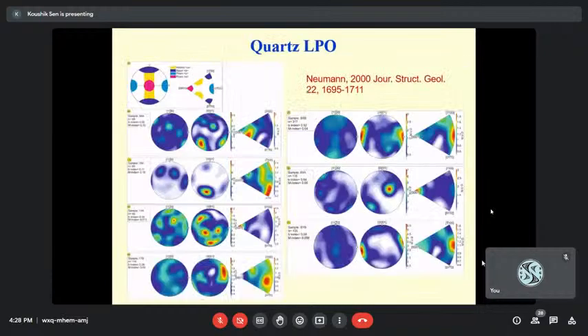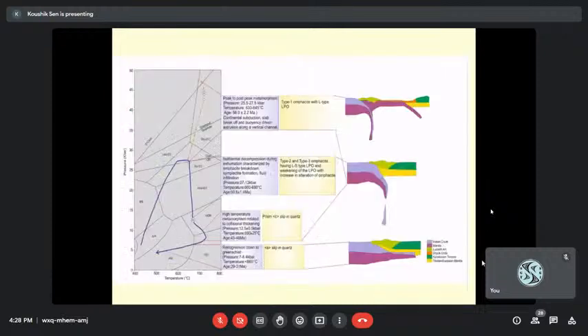Now we want to interpret this LPO in terms of the metamorphic evolution or the PT evolution that we have obtained from previous studies. Now, the type 1 omphacite or type 1 eclogite, that is the freshest of all eclogites, that is the sample 7X, shows an L-type fabric. Now, this can be assigned to the peak metamorphic conditions, say 2.5 to 2.7 gigapascal, when during the peak subduction or peak metamorphism this fabric developed, and this L-type fabric will suggest a constrictional strain regime. That means a constrictional strain regime during the peak subduction of the Indian plate.